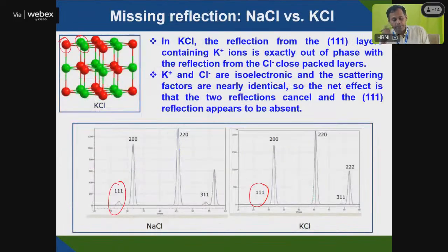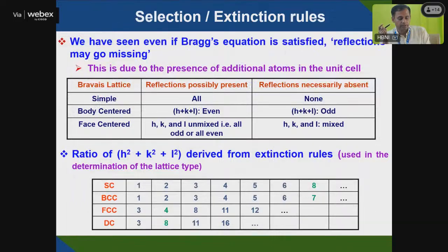But the same thing will be different if you take a neutron diffraction pattern. In neutron diffraction, you will be able to see that 111 plane for KCl. We will discuss that when we go for the neutron diffraction study. So if you see the selection rule, in general, even if Bragg's equation is satisfied, a reflection may go missing. This is due to the presence of an additional atom, as you see in the BCC molybdenum structure, the center atom. In a simple cubic, the reflection is possible; all HKL values are possible, and no reflection is necessarily absent.